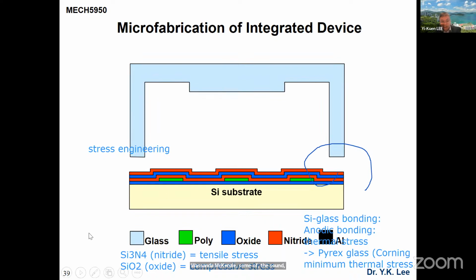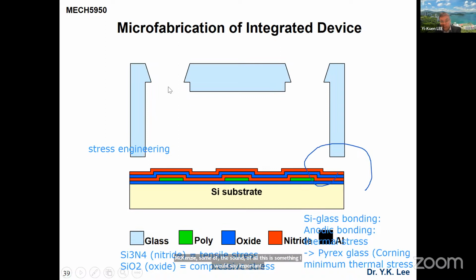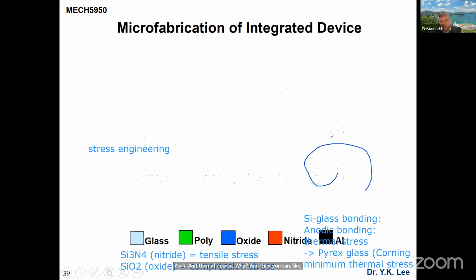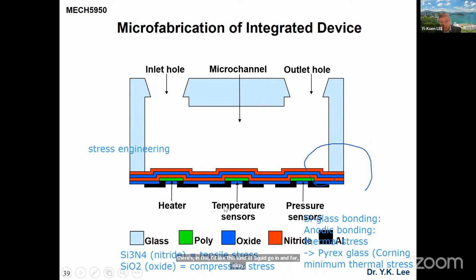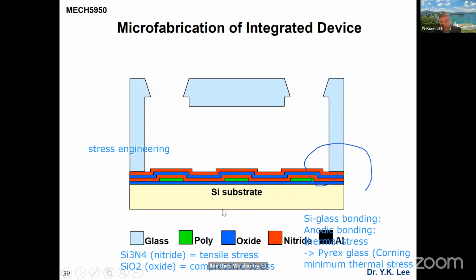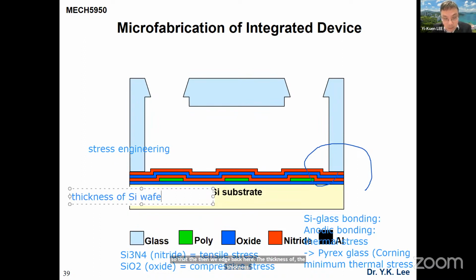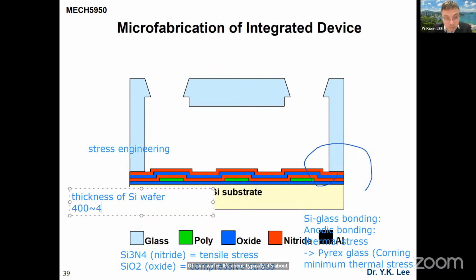Yeah. And then of course you drill a hole, right? And then you can let it be an inlet and outlet, to let this kind of liquid go in for cooling. Okay. And then you can see we also try to do an additional etch back. What happened? A typical thin wafer is about 400 micron. Okay, so then we etch back here. The thickness of silicon wafer is typically about 400 to 450 micron. Okay, so what's the problem?